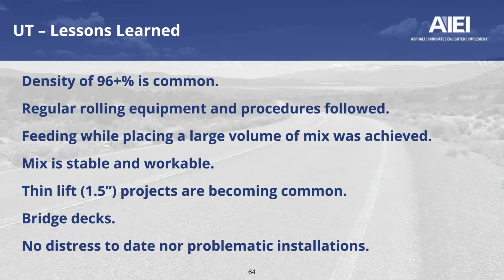Regular rolling equipment and procedures have been followed. I didn't mention out at Wendover as well as at the test strip, Staker Parsons found that with just 5 passes of the double vibratory roller, they were getting all the density they need. Therefore, they did not include an intermediate roller rolling phase at either the test strip nor out at Wendover. And the final roll was done with that very same steel roller now operating in static mode to create that final smooth surface.